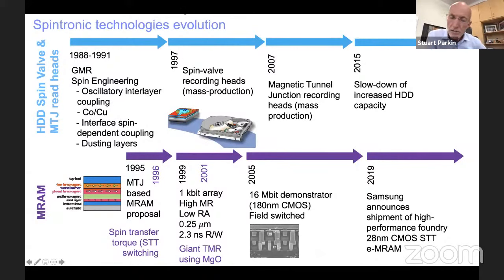And then later on in 2005, we demonstrated at IBM a complete 16 megabit demonstrator in 180 nanometer CMOS. At that time, the tunneling junction device states were switched by applying tiny magnetic fields through currents passed through copper lines next to the tunneling junction devices. But around about this time, it was discovered you could actually pass a current through the tunneling junction, and the spin polarized currents carry spin angular momentum, which can be used to apply torques and can be used to switch the magnetic moment within the tunneling junction itself. And this essentially is the essence of today's magnetic random access memory using something called spin transfer torque effects.